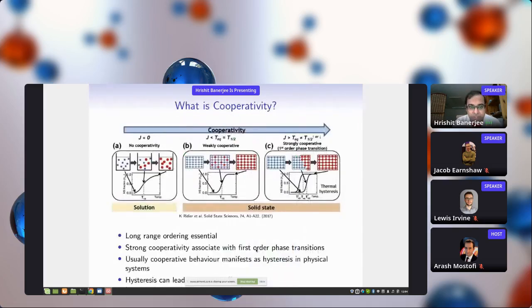So what is cooperativity? Cooperativity is the phenomenon by which you go from a very gradual, almost second order change with no cooperativity in a liquid or a solution, to an almost first order change, and for a very strongly cooperative system, you also have hysteresis. So how the transition happens between the low spin and the high spin states is what determines the cooperativity, and long range ordering is basically essential for cooperative transitions. Strong cooperativity is mostly associated with first order phase transitions, and this cooperative behavior is manifested as the hysteresis, as you see here, and which was also shown experimentally.